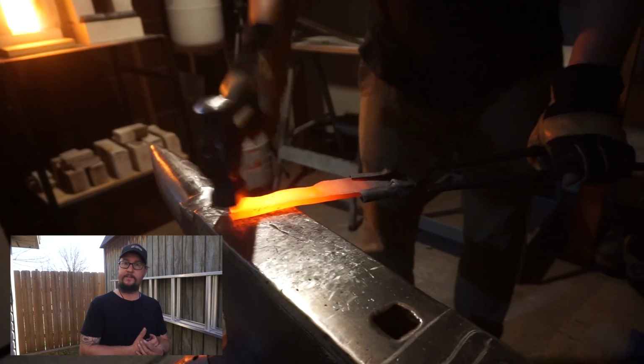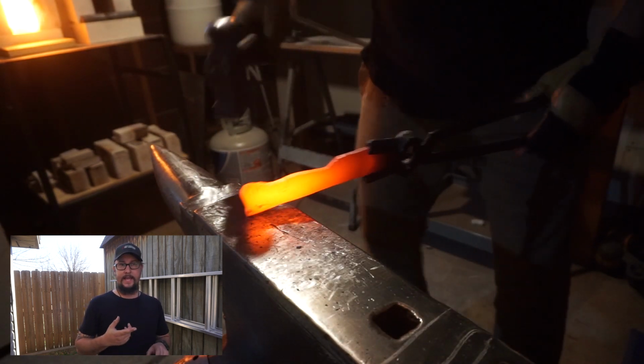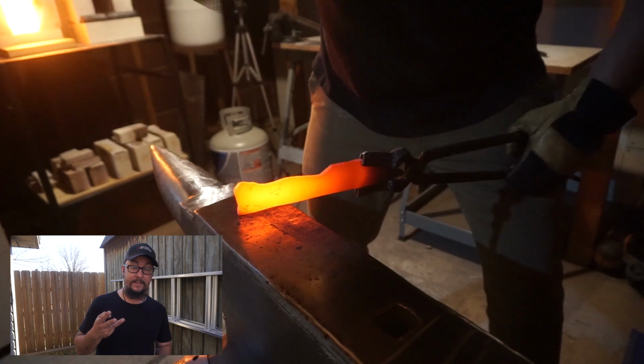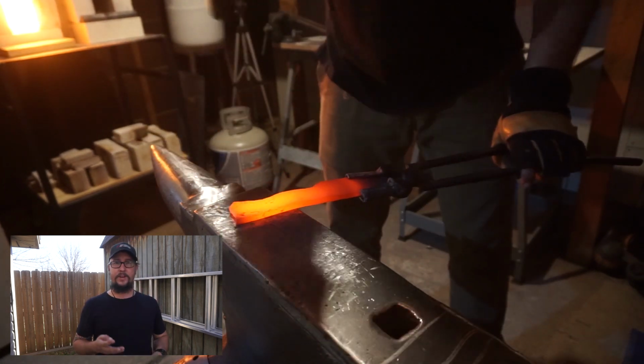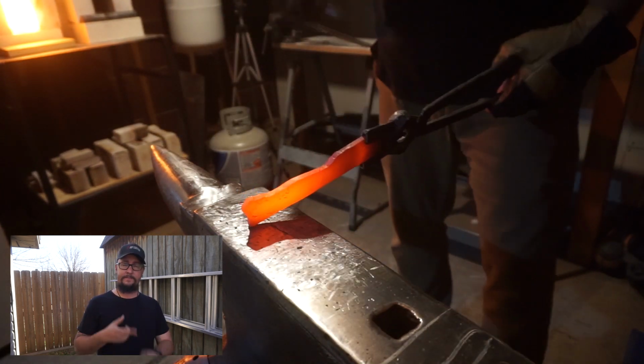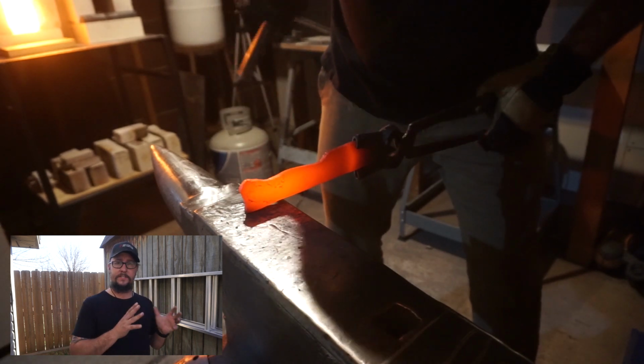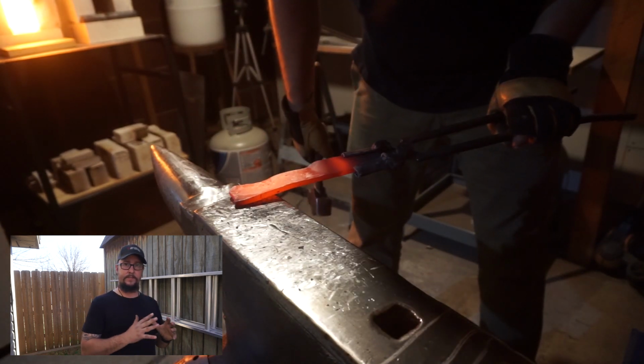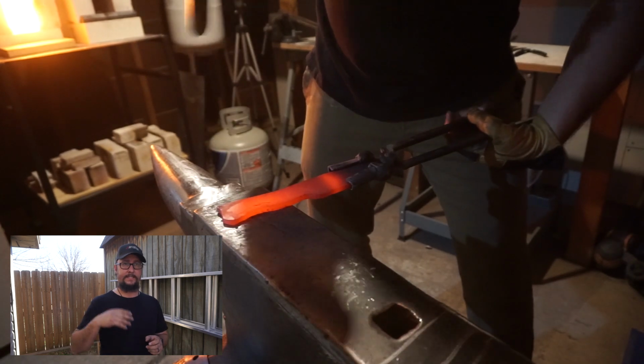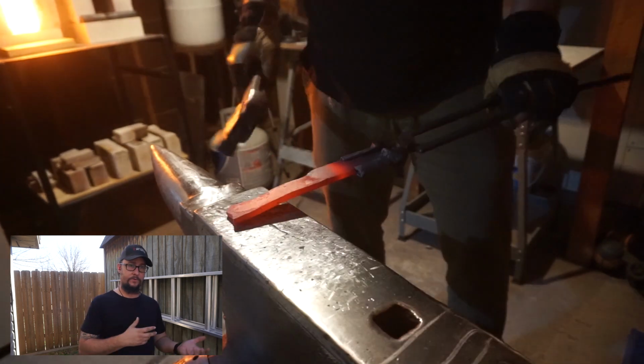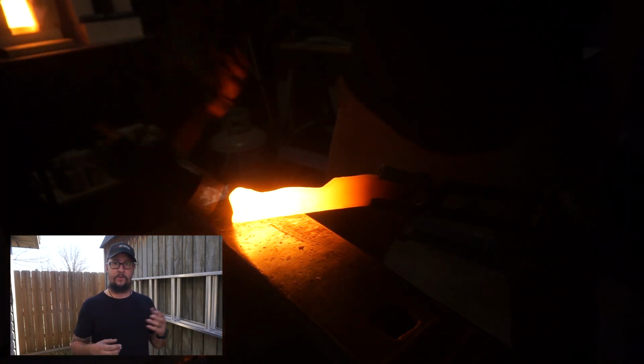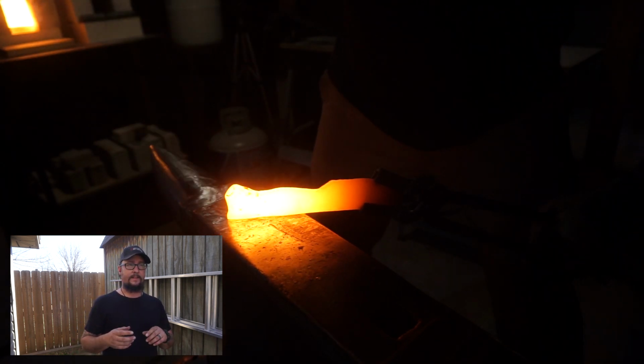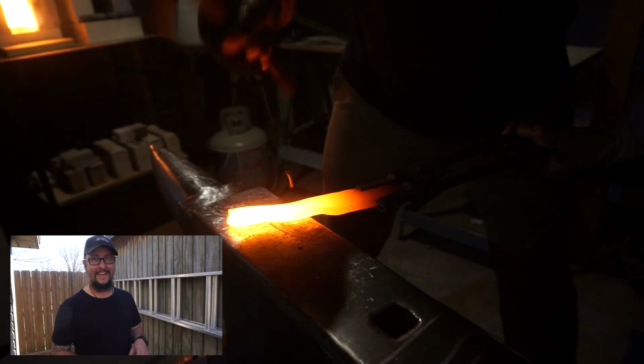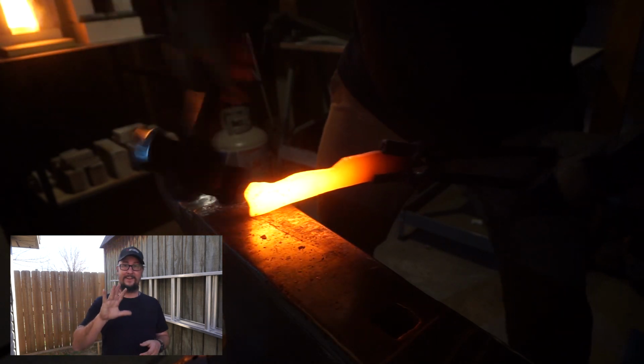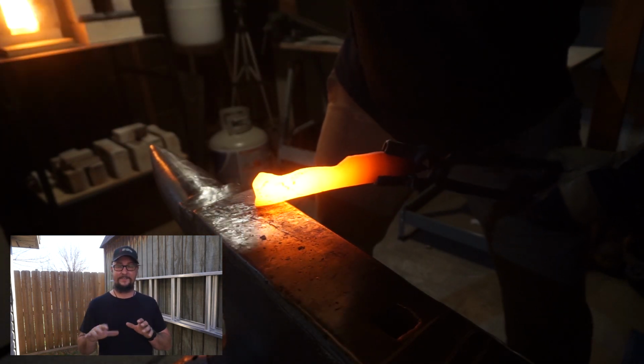It's not as forgiving as something like 1080, 1084, 1070, 80CrV2, 5160, 15N20. All of those steels are very simple steels to heat treat. But whenever you get into 1095s or some of the tool steels and things with vanadium and chromium and all that, even though 80CrV2 has some of that in there, it's still a very easy steel to work with and very easy steel to heat treat.